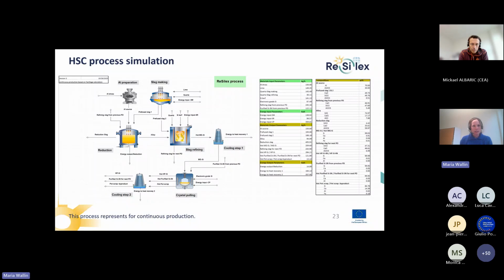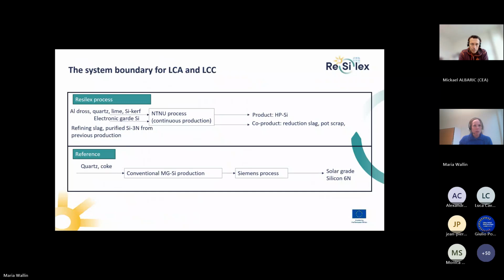And in the LCA case, we set the system boundaries, both for LCA and LCC in this project, around the whole process. So we start with Resilex, where we have the dross and quartz and everything. And then our process is the Resilex process all the way to the high purity silicon, this 5N. And we compare it with the Siemens process, that is the commercial process.